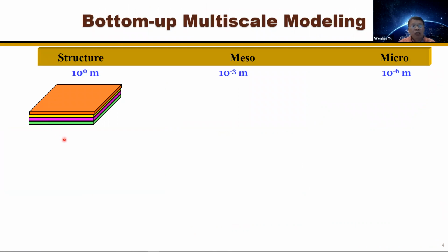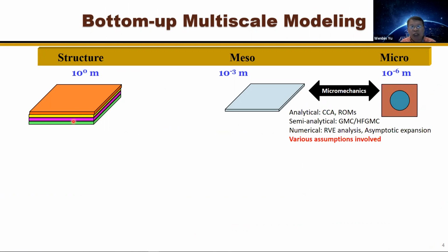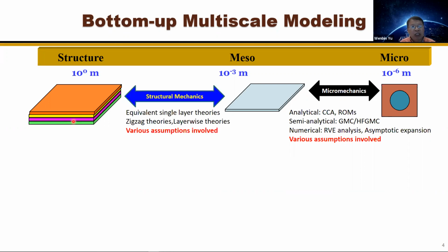Traditionally, for example, with a fiber reinforced laminate, we have so-called bottom-up multiscale modeling. We start from some kind of unit cell, an idealized representation of the material mixture, then use certain micromechanics calculations, which could be analytical, semi-analytical, or numerical, to get so-called nominal constants. Then use some structure theory, the most popular one being classical lamination theory, to construct the structure theory, then do the structure design analysis.